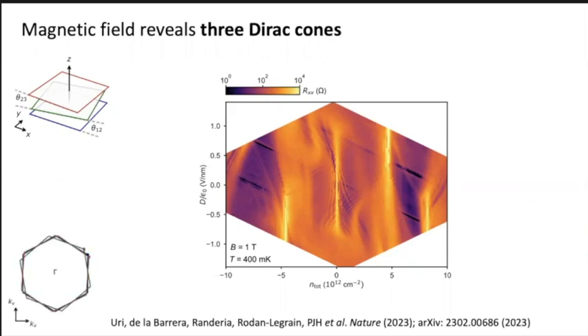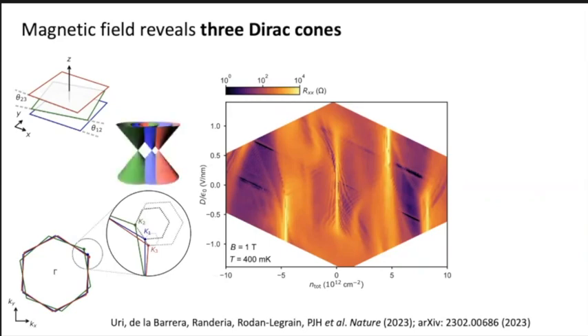If you look in reciprocal space, you have the Dirac cones of each of the layers, and they're rotated by angles. If you zoom in, you can see the Moiré unit cells spanned by layers 1 and 2 and by layers 1 and 3. As a result, you have these three Dirac cones, which don't form the flat bands of magic angle trilayer graphene because they're not at the magic angle condition.